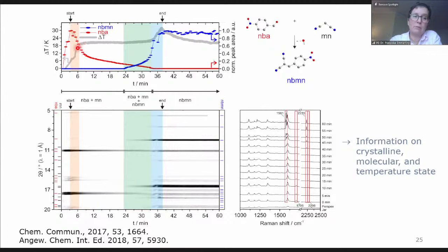Then if you look at the diffraction data, you see that the intensity of the reflections decreases and we start to form the product. And in this blue area where the product formation sets in, the temperature rises a bit and then goes down again to the plateau we saw before. So you can see in this example that the heat of formation really contributes to the temperature within the mill, and that it's not the collision with the balls and the milling jar that gives rise to this temperature, but actually the heat of formation.